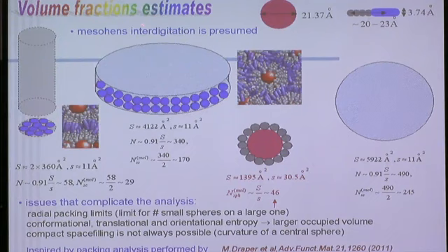So first we assume that there is interdigitation of our mesogens, and we know again from the previous talk that the chemical nature of this is pi-pi interaction between two aromatic groups that are in oppositely pointing mesogens. So we can just think about some cylinder and subtract the spherical particle and calculate how many chains we can get inside if they can closely pack. It's something like 29 for our dimensions. Then for the disk-like particle, we can theoretically pack 170 particles, quite a lot. Also, we assume interdigitation here. And for spherical particles, it is something like 245.